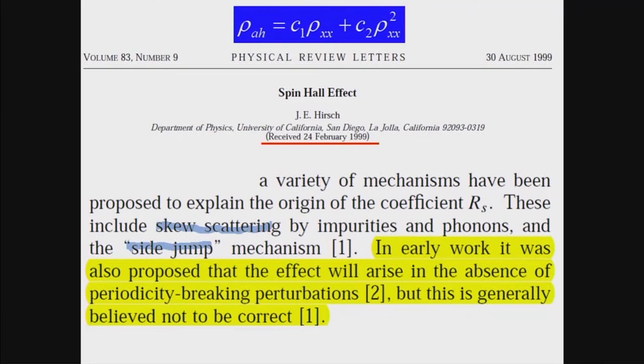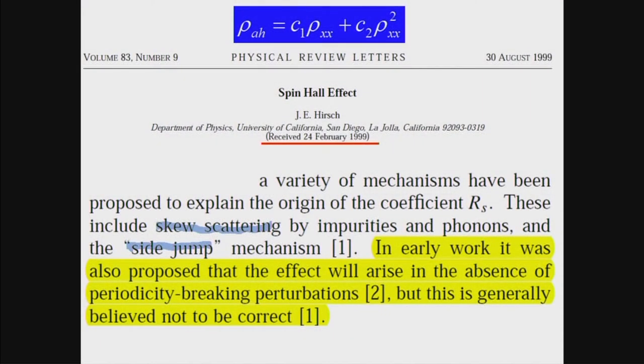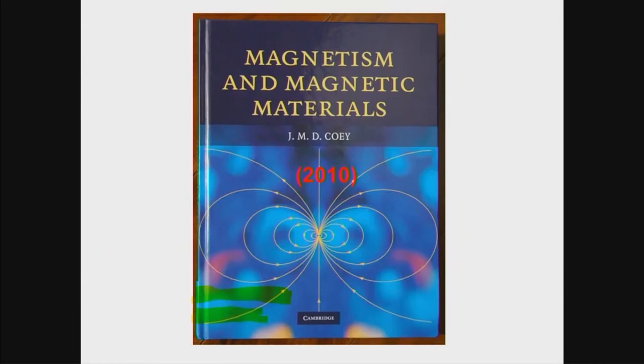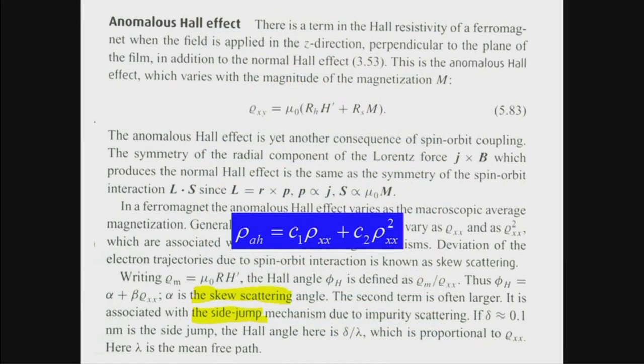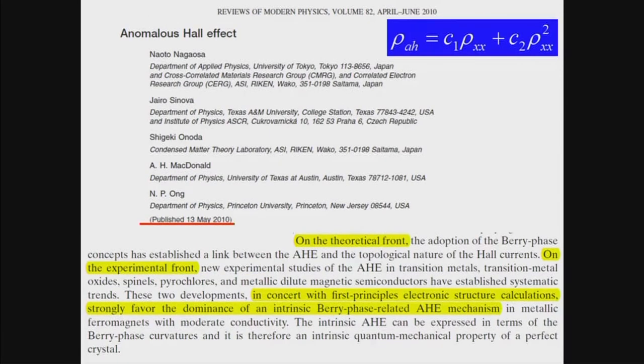This is a quite famous paper in our community, on the spin Hall effect, by Hirsch, who is now better known for his H-index. Sandra just mentioned the H-index a lot of times, and it is actually from Hirsch. In this paper, he said it should be skew scattering and side jump, and that the intrinsic mechanism was also proposed in the early days, but it's not true. And in this quite well-known textbook in our community, it also mentions skew scattering and side jump, without even mentioning the intrinsic one. So on the one side, people believe it's a purely extrinsic effect, but if you look at the paper by Nagaosa, Sinova, Allan MacDonald and those theoreticians, the abstract clearly says that, in concert with first-principles calculations, it strongly favors the dominance of the intrinsic mechanism.